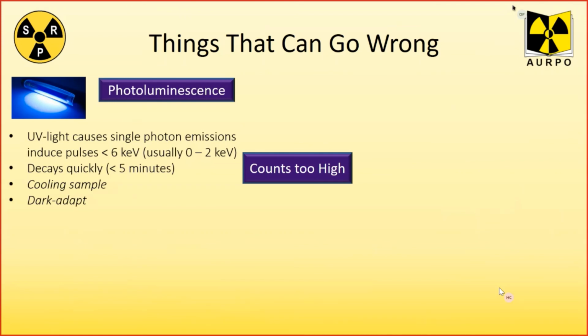This is known as dark adapt. For example, seaweed needs to be stored in the dark for many hours to reduce counts from millions of DPMs to thousands. And if you do measure a sample that is photoluminescent, you'll see quite an erratic series of results.